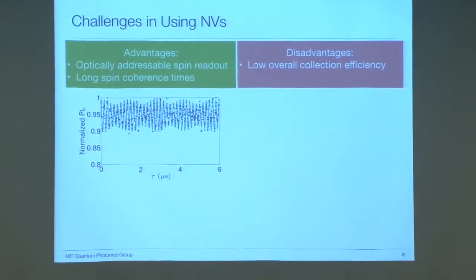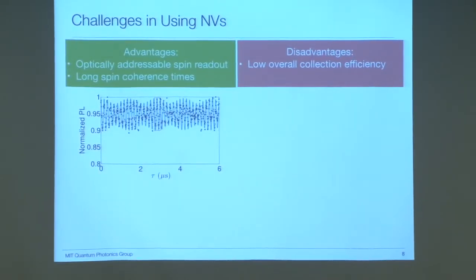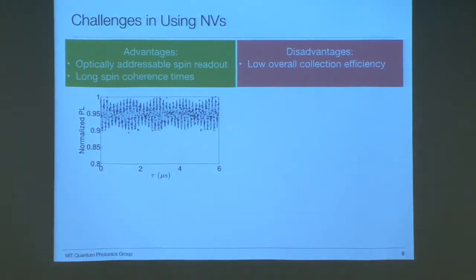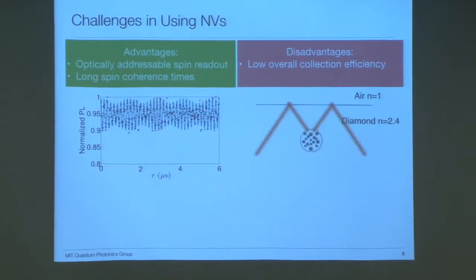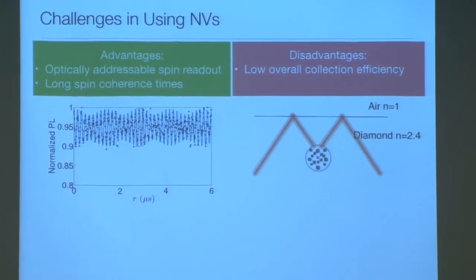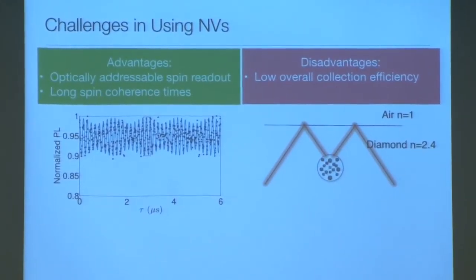So the advantages of NV centers are optically addressable spin initialization and readout, and long spin coherence time. And the disadvantage is also obvious. Overall collection efficiency from a single NV is low. That's because of the index contrast at the diamond and air interface. For optical entanglement of two NVs, the count rate is only about 300 kilocounts per second.